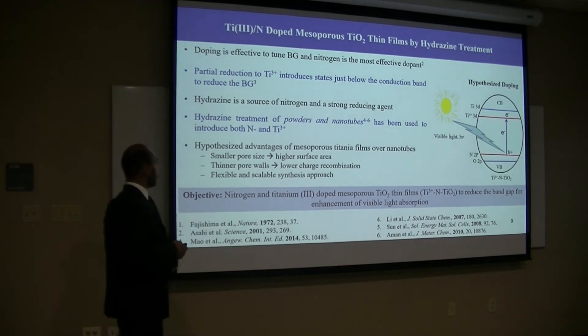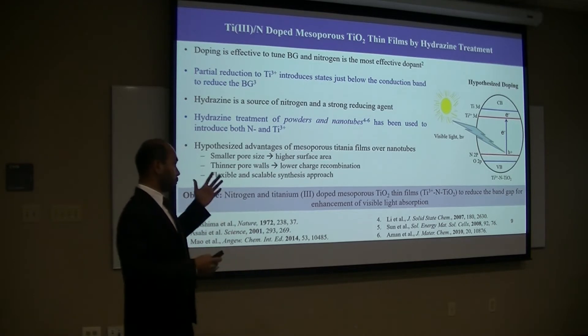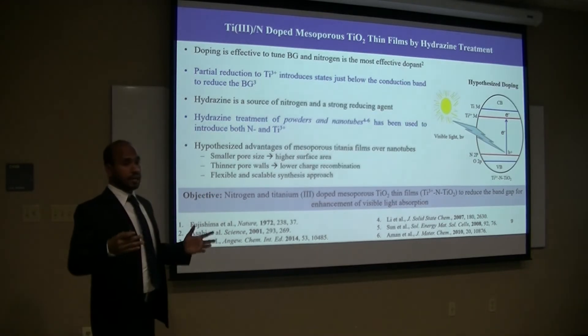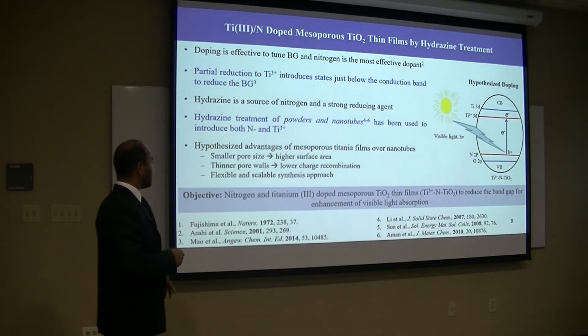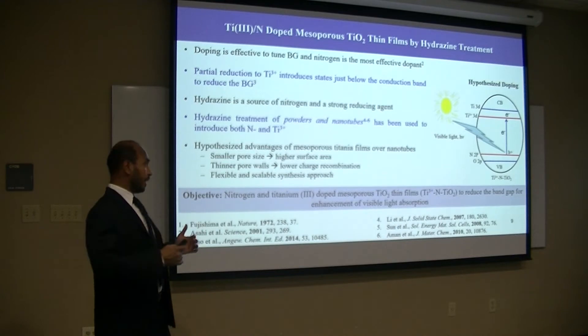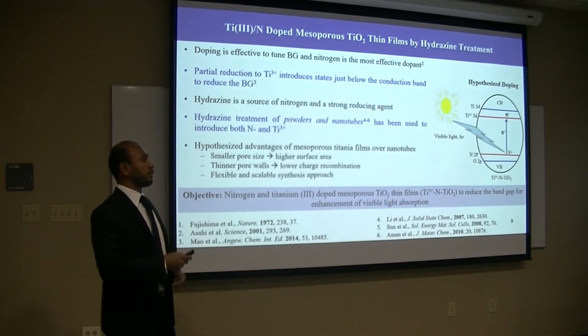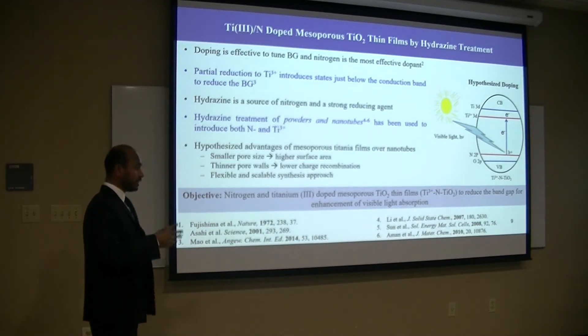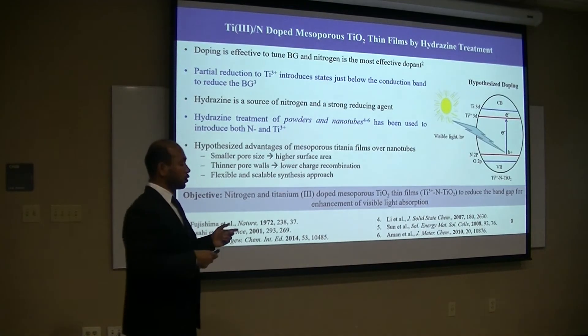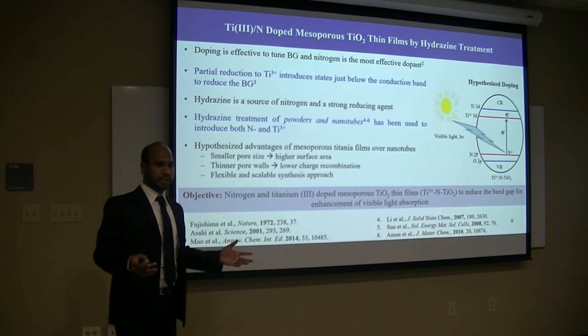As I mentioned before, the mesoporous titanium has several more advantages over other morphologies like nanotubes: it has smaller pores, which results in high surface area; it has thinner pore walls, which results in lower charge recombination; and finally, it is a very flexible and scalable approach. So in these studies, our objective is to prepare titanium and nitrogen co-doped mesoporous titanium thin films by hydrazine treatment to reduce the band gap and enhance the visible light activities.